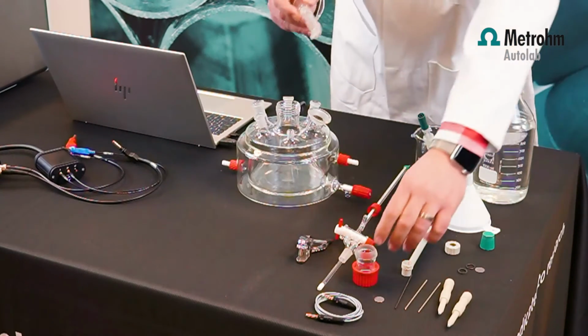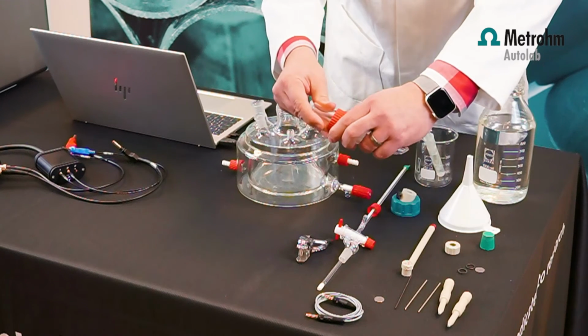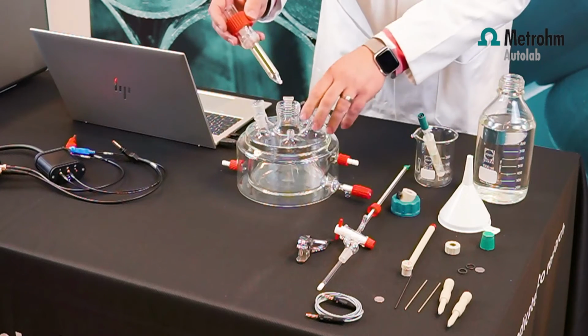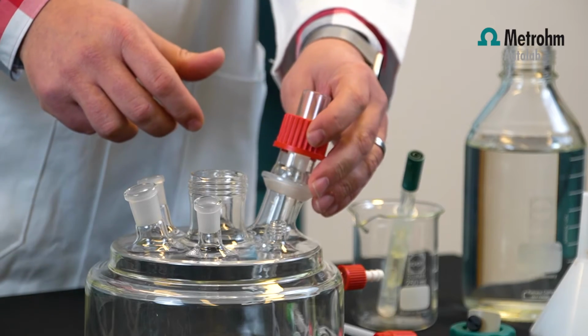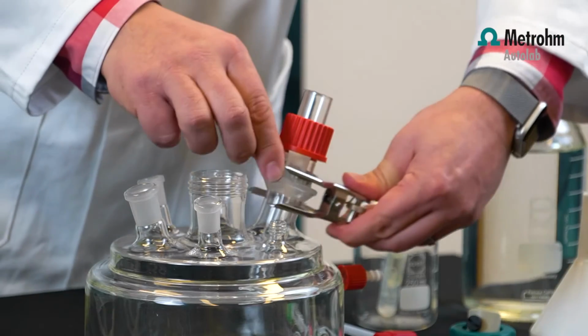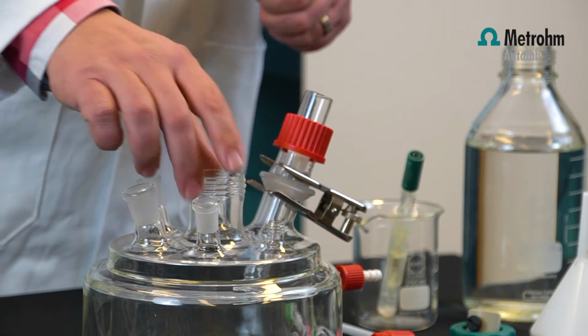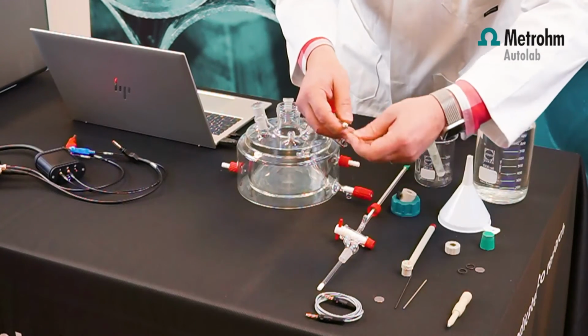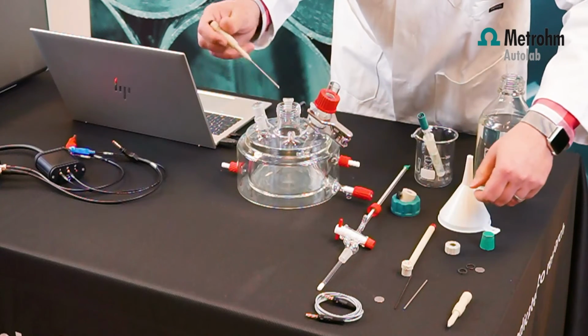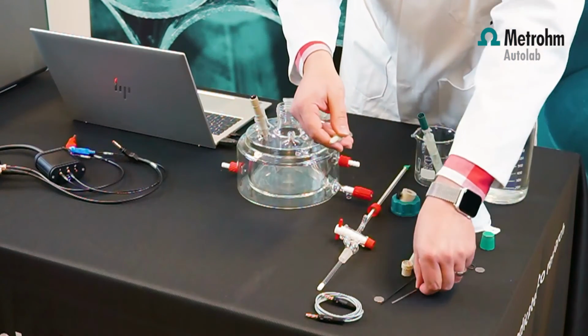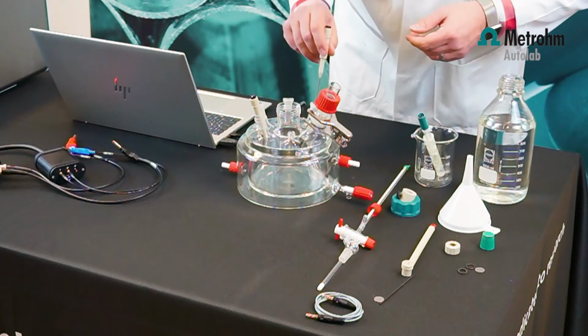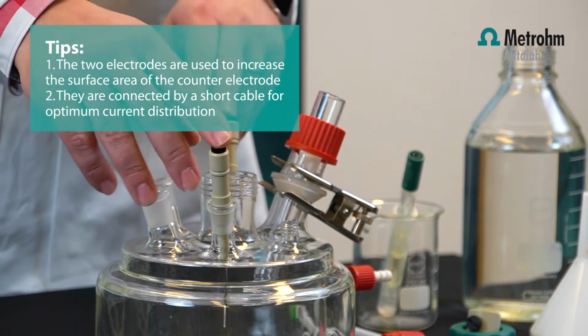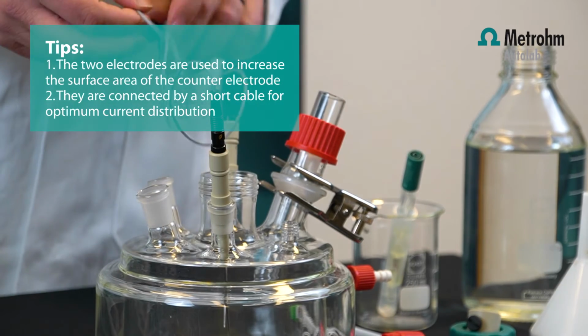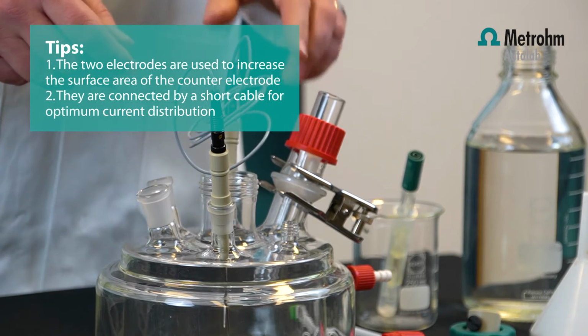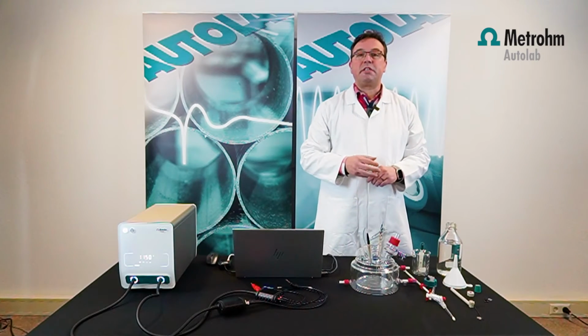The Luggin capillary, this one, is fitted with a spherical ball joint, so you can just insert it like this. And this you can put into position in the corrosion cell, like this. Then we have the counter electrodes. Counter electrodes go in here. So we have the stainless steel on one side and a stainless steel on the other side, like this. And those two are connected with a small cable to increase the surface area of the counter electrode. And the surface area of the counter electrode is important for a proper current distribution. Standard, it comes with stainless steel 316 electrodes.